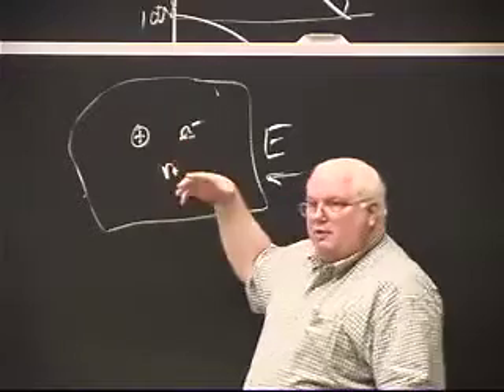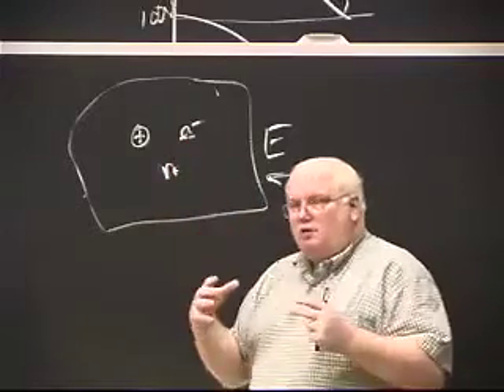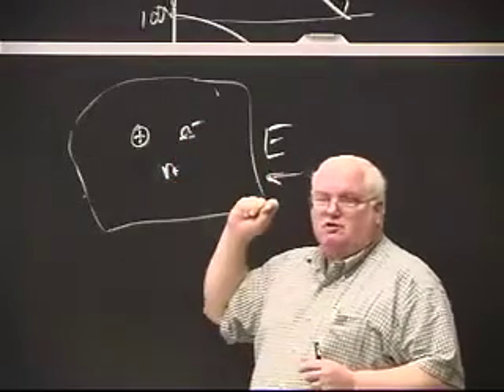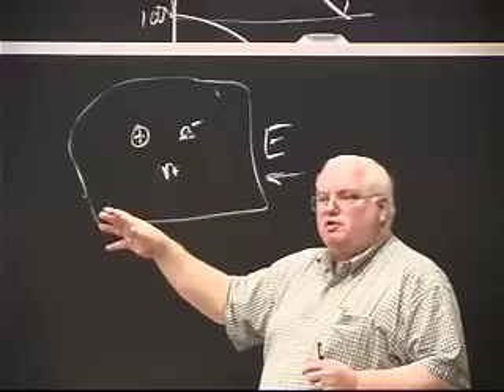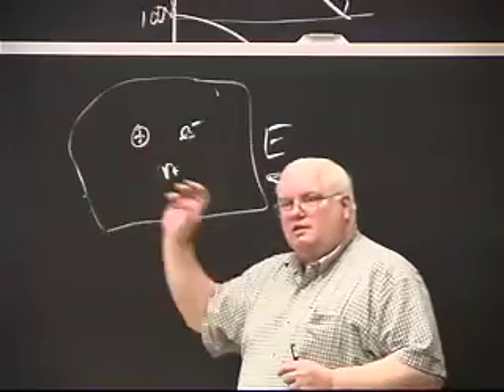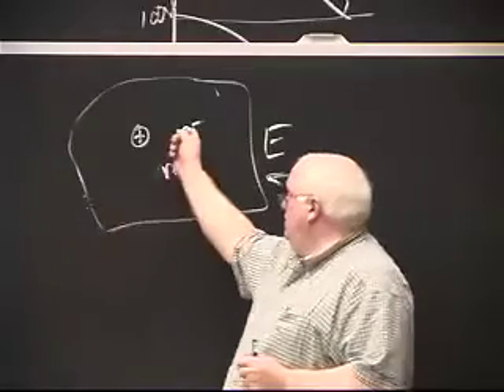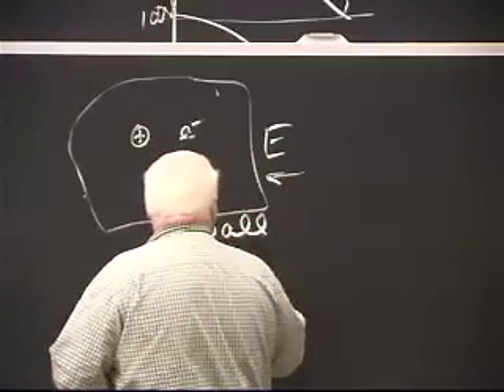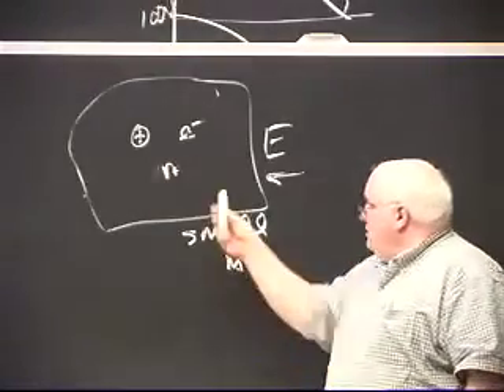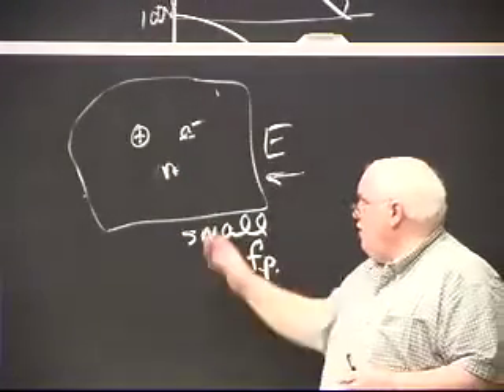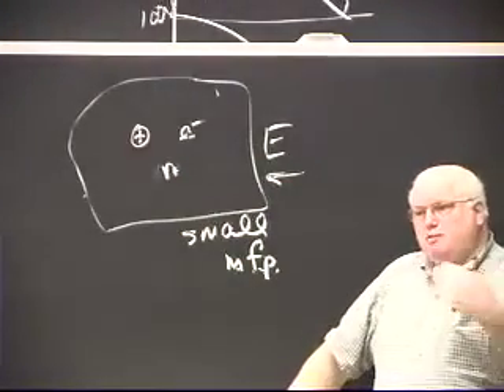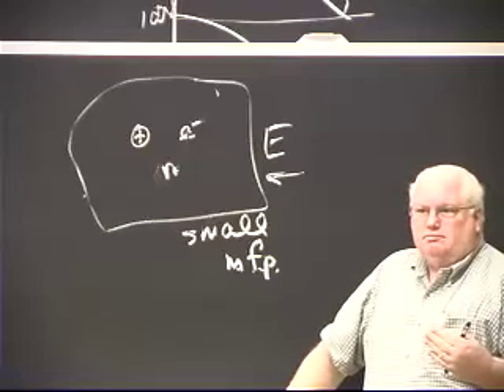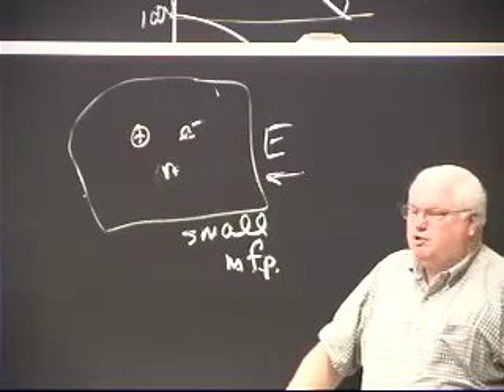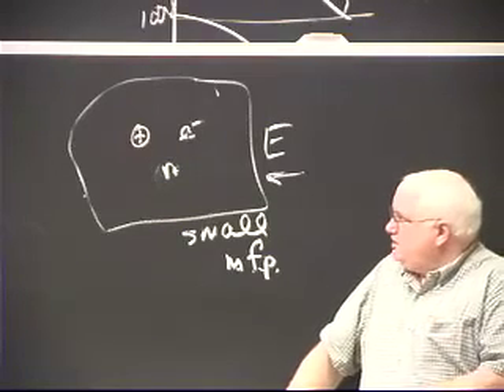But what happens is if I'm in a high pressure arc where all these are relatively close together, that electron hits one of the others and gives up some of its energy to them before it can get accelerated again. And so when they're close together, they have what's a small mean free path. Okay? The distance between them is so small that the temperature difference between them, because they're banging around together, is going to be small. And so they're within 1 or 2% of the same temperature. And this is a plot of temperature.